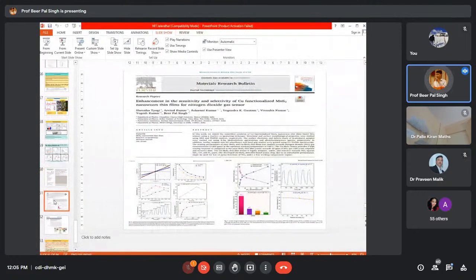This is another work: as I told you, one of my students working on MoS2 successfully fabricated a TFT using MoS2 thin films deposited by the sputtering technique. She also had MoS2 nanowall thin films functionalized with Cu doping, and she sensed nitrogen dioxide gas using the Cu functionalized MoS2 nanowalls. Although it is not a metal oxide, I put that slide in this presentation just to show the results.